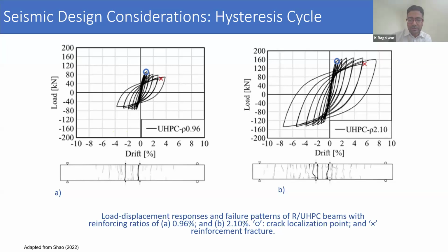Under both monotonic and cyclic loading, increasing the steel ratio helps reduce the rate at which the load capacity drops after the crack localization. It also encourages development of multiple localized cracks.